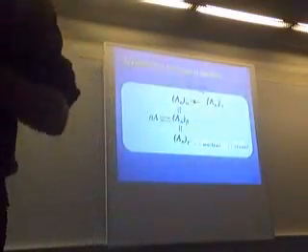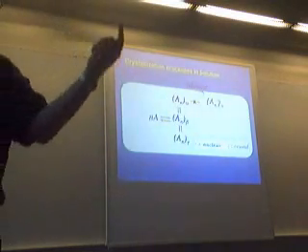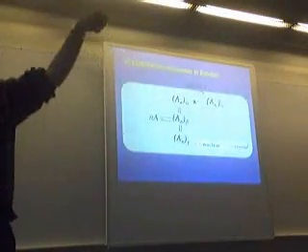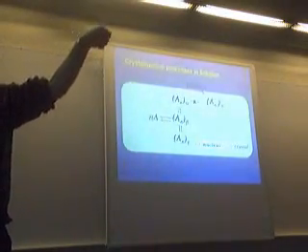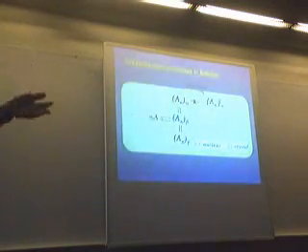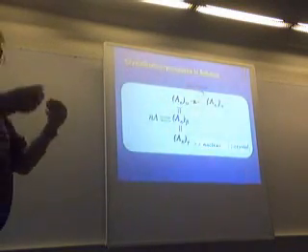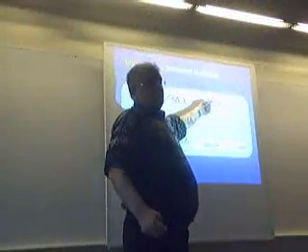And therefore we shall see that the entire system will be driven now to a second polymorph, which is thermodynamically less stable as compared to the stable polymorph. I think this is another advantage, but it has many common features with what Professor Saito demonstrated, in the sense that there we have two equi-energetic systems, whereas here I have two systems which are different in energy. And I can draw the entire system toward this particular polymorph, even with the assistance of a very small additive which is present in the solution, and this is done by decomposing the appropriate clusters which are leading to the formation of the stable polymorph.